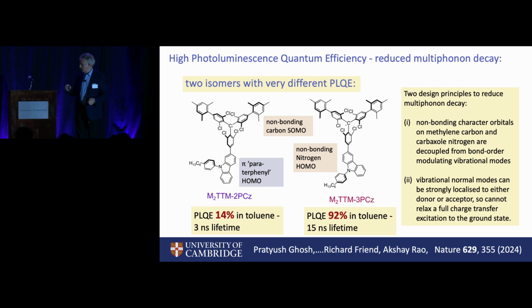Well, the answer is that what it has done is to tip the HOMO state from being a state primarily of nitrogen non-bonding character, which is the one on the right, to one that looks like a pi bonding character, and that then couples very strongly to high-frequency ring stretch modes on the phenylene bits, and that switches on vibrational coupling. So if we have the design rules, which are set out very carefully in that paper, you can actually engineer luminescent materials down in the red and the infrared, which is pretty useful if you want to head towards the biological window, sort of centered around 800 nanometers.